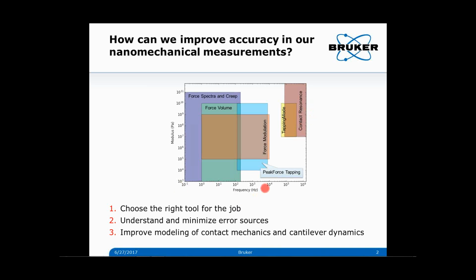So here we have this plot. We have frequency on the bottom axis and modulus on the left axis, and you can see that these different modes have optimal regions in the frequency-modulus space. If you choose the contact resonance, that maybe isn't the best for very soft materials. Force modulation maybe is good for the intermediate range, but not great for the highest moduli or the highest frequencies. Force volume and peak force tapping are in the middle also, and force spectra is great for low frequencies.